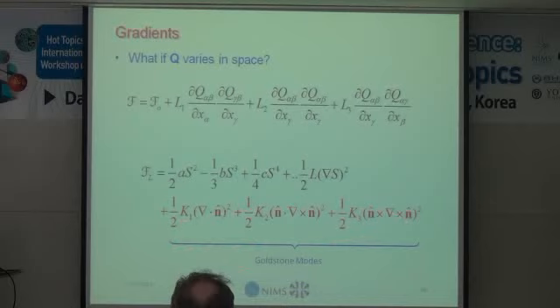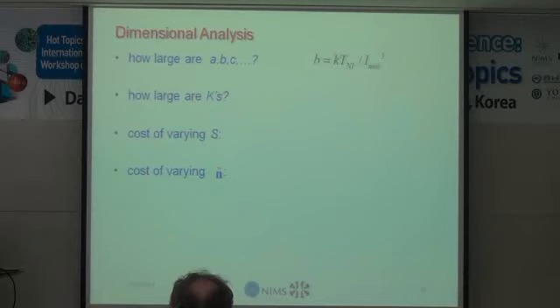But these are the Goldstone modes. These are the low energy excitations which enable us to easily deform these materials. So it's interesting to look at how big these coefficients are. A, B, and C are the coefficients associated with changing the eigenvalue, the scalar order parameter, and the K's with just changing the director distortion. Just from dimensional grounds, you have free energy density, so A, B must have units of energy per volume. The only energy we have is the nematic interaction, so kT and I is a measure of that. And the only volume we have is a molecular volume. So B has to be this order.